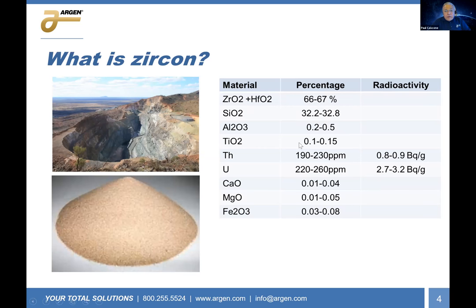And the reason why is because this is the composition on the right-hand side. And the reason why you could determine the time is because it has two radioactive materials, thorium and uranium. And you can see the radioactivity is not incidental. It's quite significant. You don't want to put that next to a soft tissue. The material is essentially silica with this zirconia, and we'll talk more about this percentage. But this is what the sand looks like. And now we're going to take that sand and we're going to extract the zirconia from it.